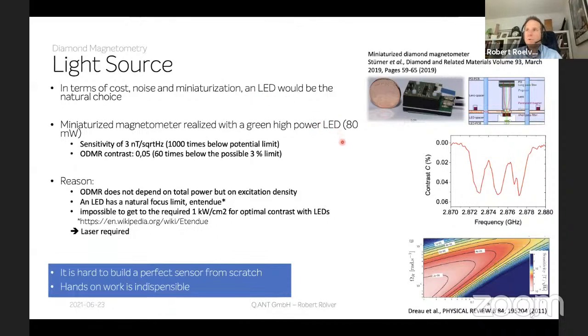Yeah, we built this up, and what is also published in this paper and can be seen is that the contrast of the detectable magnetic resonance is very low. It's only 0.05% in this case. And this is also then resulting in a sensitivity of 3 nanotesla, which at that time was already pretty good, but it's still 1,000 times below the potential limit, as shown in proof of concept experiments with this 1 picotesla per square root hertz. And what we found out during the development is that the magnetic resonance contrast